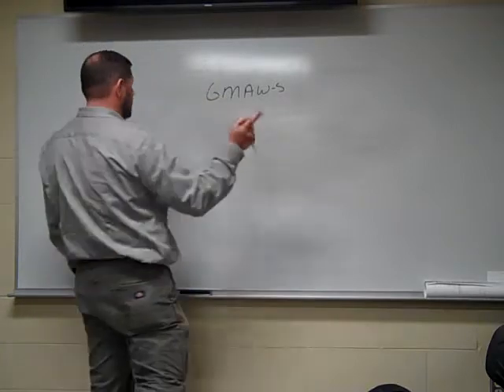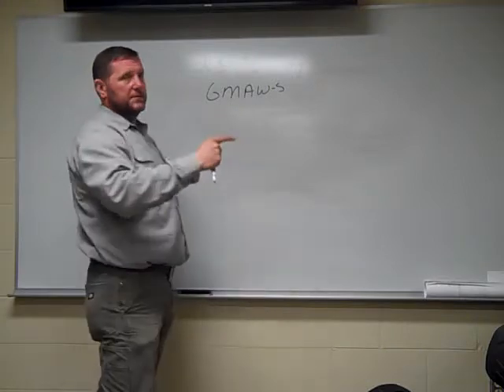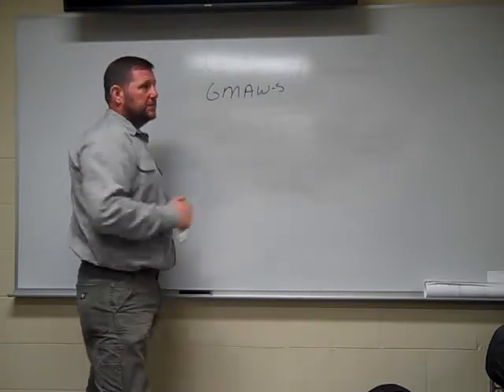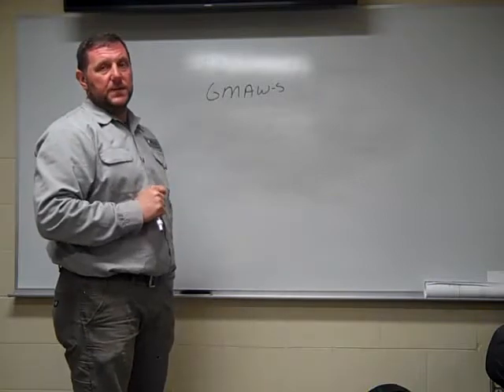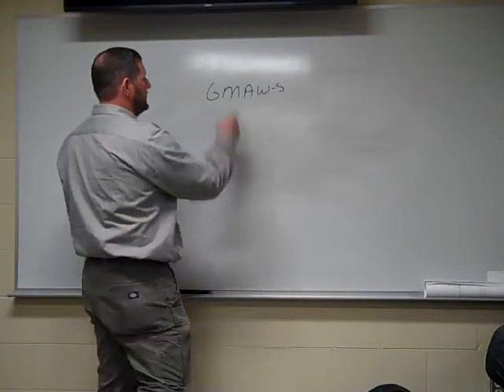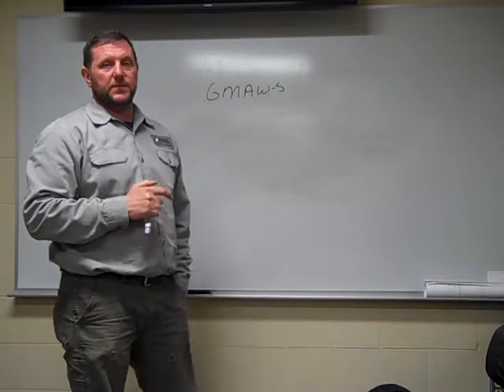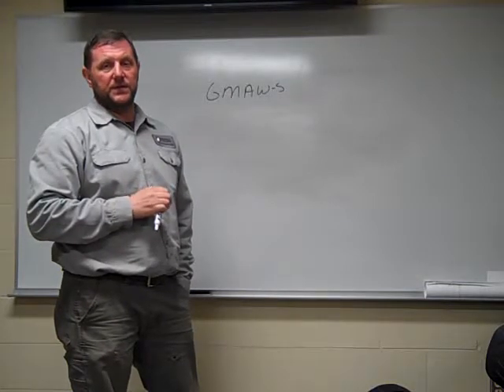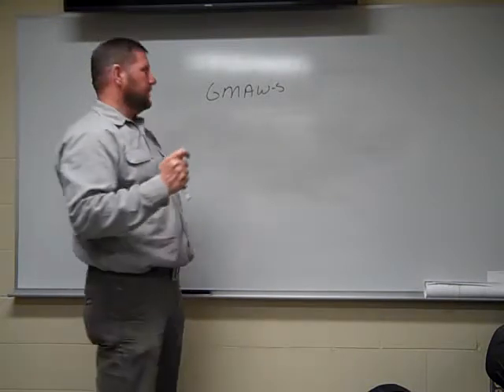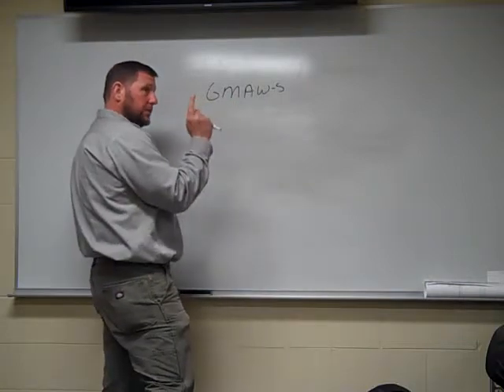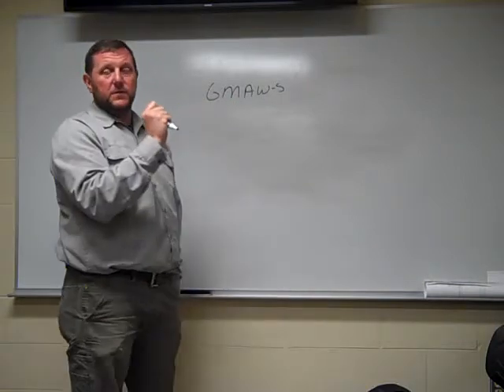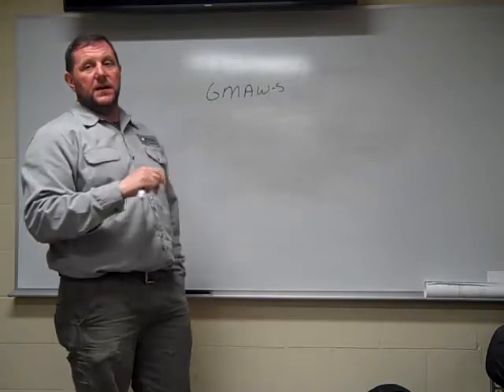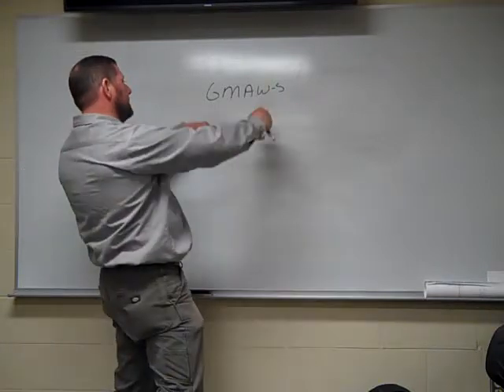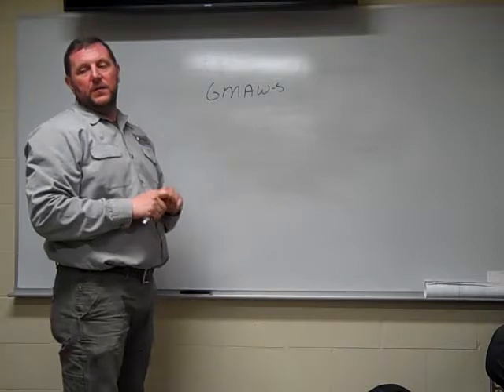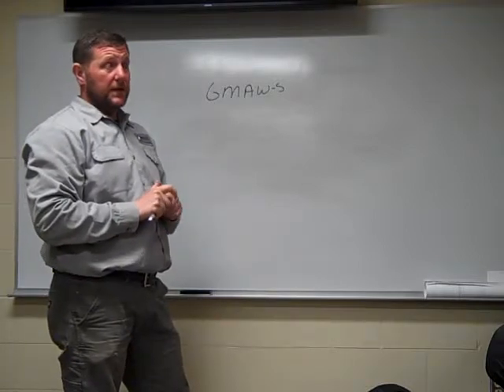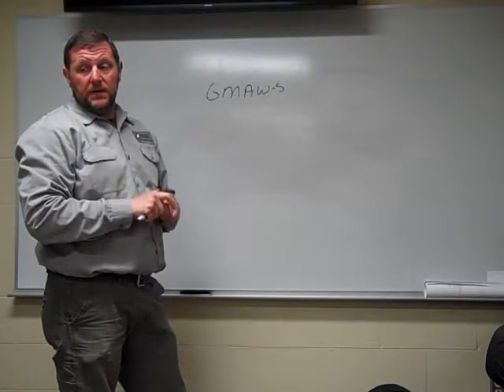A lot of times you just don't want to keep welding. If you're doing a piece of 1 inch and you got to put 15, 16 welds on it or whatever it may be, make sure you just don't keep welding. You want to make sure that your interpass temperature does not increase over 350 degrees. So what does that mean? Do a pass, let it cool a little bit, do another pass, let it cool a little bit. You just don't want to weld that thing solid, because what you're doing is you're adding a lot of heat into that base metal, and you'll burn out a lot of the properties of the metals.